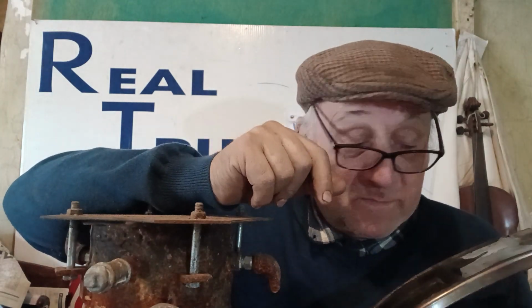Now, in the video, I'm after showing you of the brazed joint, I used brass for that purpose to braze the piece of mild steel bar that I've shown you there. In the case of the joint on the tank, I used 55% silver solder. With delicate joints for stainless or anything else, where the pressure is not fantastically strong, where it's not really brutal, where you're not putting a big bolt on it and hammering it, by going high silver, you get a better joint, better capillary action, and better sealing. So you get what you pay for.